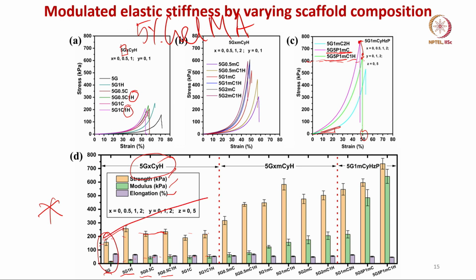But the substantial improvement you can notice is here. If you compare 5% GelMA with 5% GelMA and 0.5% modified carboxymethyl cellulose, the strength increases from almost 150 to roughly around 300. The elastic modulus also increased quite substantially, to close to 50 or 60 kilopascal. Now, on this baseline matrix, once you start adding 1% hydroxyapatite, the strength increased. Now, you change the matrix from 5% GelMA to 1% modified carboxymethyl cellulose, and if you add hydroxyapatite there, the strength further increases, and the elastic modulus also further increases.